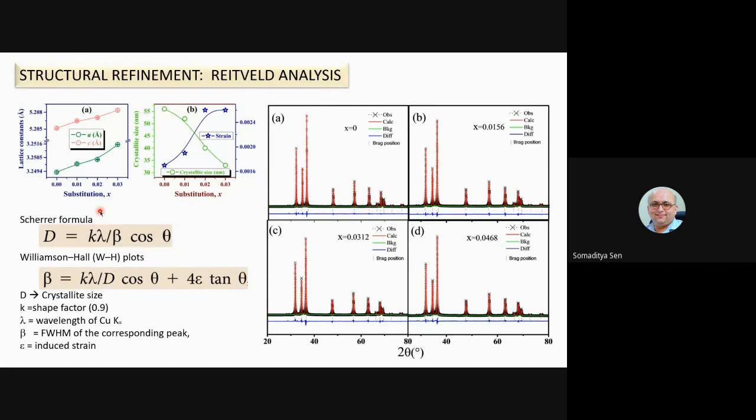So these are the lattice parameters that have been found for one system. I'm not going to detail many other systems, just one. I think this was silicon-doped zinc oxide. We got this behavior that with the substitution, with 3% substitution, the lattice parameters have increased. Now, when you put a foreign element, what changes can you think of?